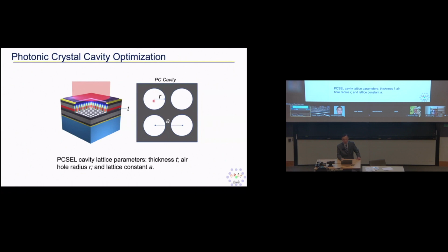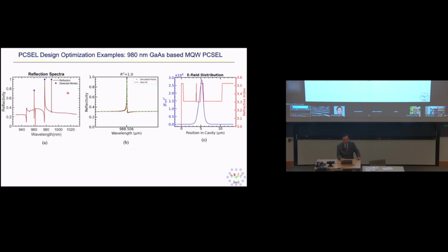So you have index contrast between air, which is one, and the index for gallium arsenide, let's say around 1 micron, about 3.5-ish. And the lattice constant A here, as well as the thickness of the PC layer and the index contrast, are the key parameters we need to consider when we design the lattice. And here, just to choose an example, a 980 gallium arsenide-based heterostructure cavity design.